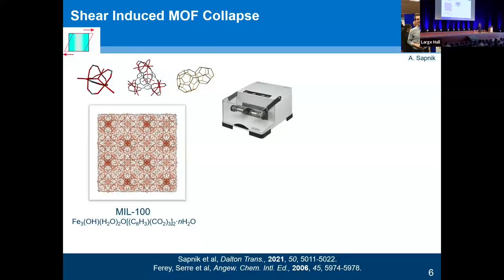Some wonderful work done by Adam Sapnick has been looking at shear-induced collapse. So what happens when you apply stresses sort of like this on a MOF? Adam chose MIL-100. MIL-100 is a fantastically complicated system. Bet you wish he hadn't chosen that now, but he did. Composed of iron oxide trimers connected by benzene tricarboxylate ligands. So there's one building unit, higher order super tetrahedra, and then an even higher order cage system.